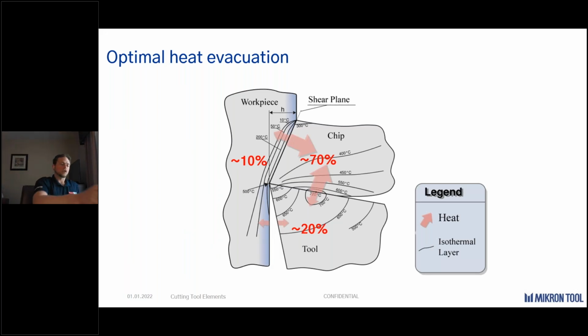Optimal heat evacuation as we get into the cutting edges of a drilling operation itself, right? The workpiece should only absorb a little bit of heat. The tool should be under about 20%. If we look at the generalized heat graph on an optimized chip, we don't want to reach anything more than about half the melting point of cobalt. We see that being portrayed right in the center there at about 700 degrees centigrade, from the point of all the other heat being pushed into the chip and evacuated.